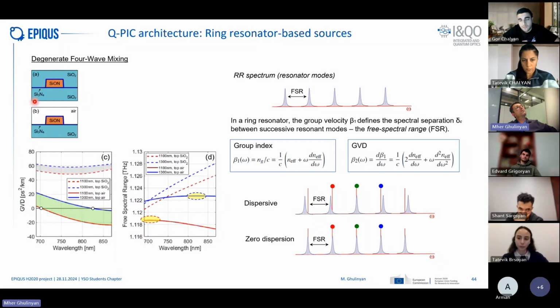material that is very similar to silicon nitride. We did the group velocity dispersion studies to understand where we could expect to have zero dispersion, so that the free spectral range, so the separation of different resonances of a ring, are constant, so you generate efficiently.